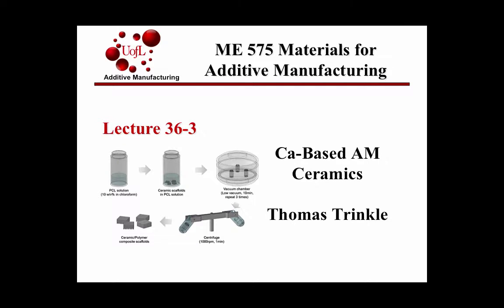I'm Thomas Trinkle again. I'm going to explain this picture while I'm here because it'll take a while to get back to. So we're using calcium ceramic and a PCL solution. You take your PCL solution with a 10% weight volume ratio of chloroform, and you put your ceramic scaffolds in it, and you put it in a vacuum chamber, and then you use a vacuum chamber 3 different times to ensure that you get a proper mixing. And then they produce their ceramic polymer composite scaffolds.